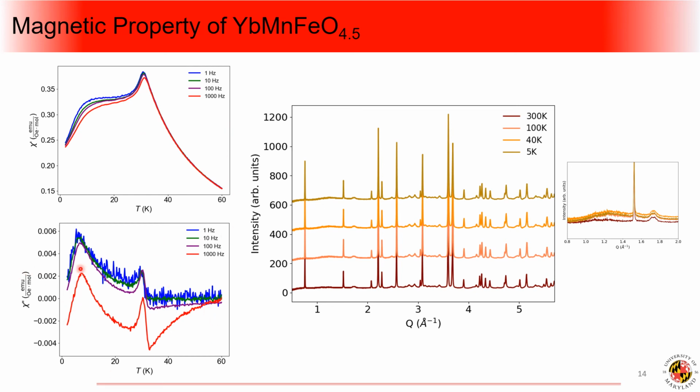It also turns out there are two transition temperatures, one at 30 and another at 10, which I have no clue about. I still need to figure out what is happening here. Anyway, in the neutron diffractions, we observed that the short-range two-dimensional magnetic ordering is greatly suppressed after the oxygen uptake. As you can see, the peak disappears, right?